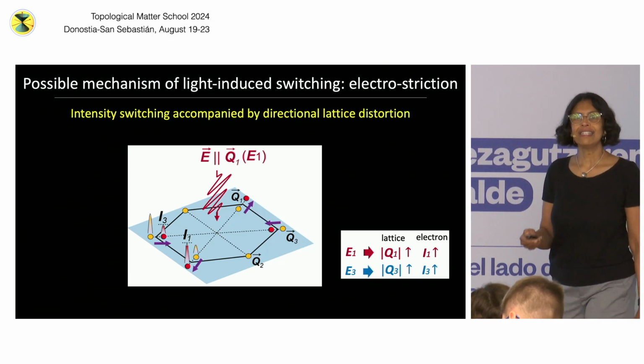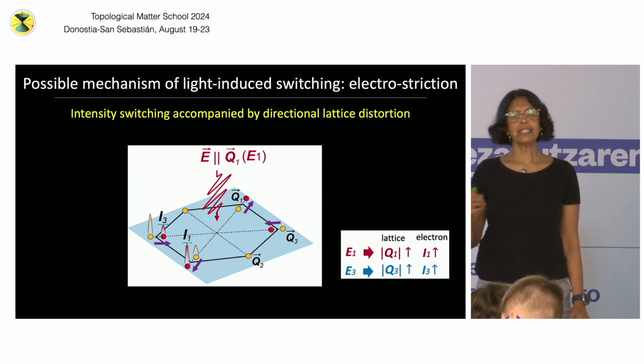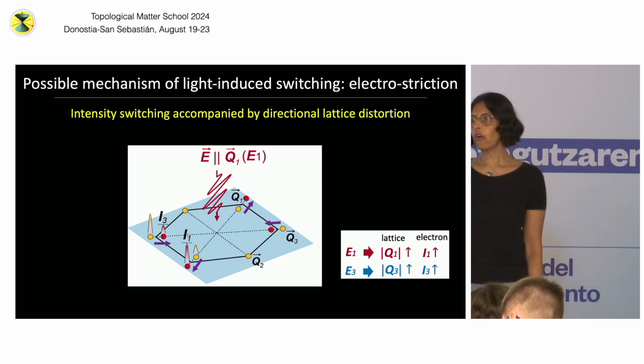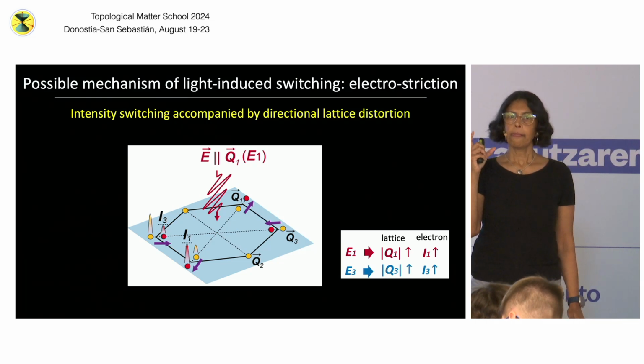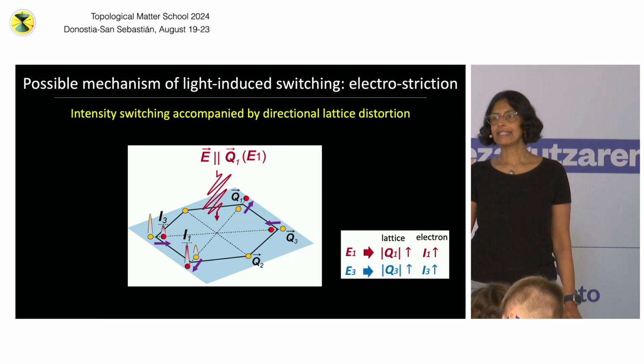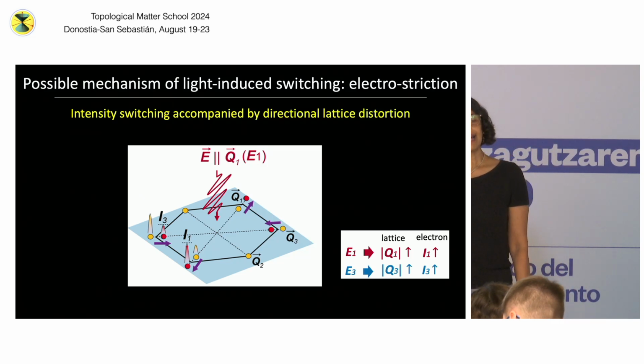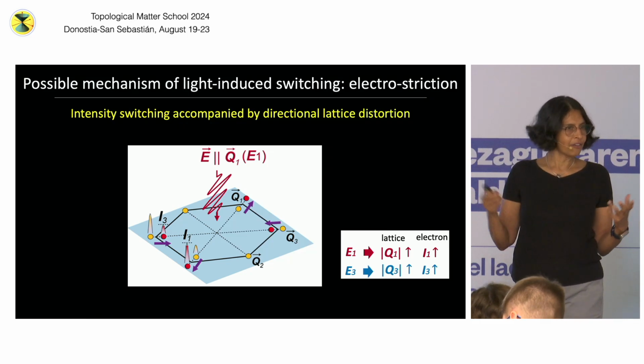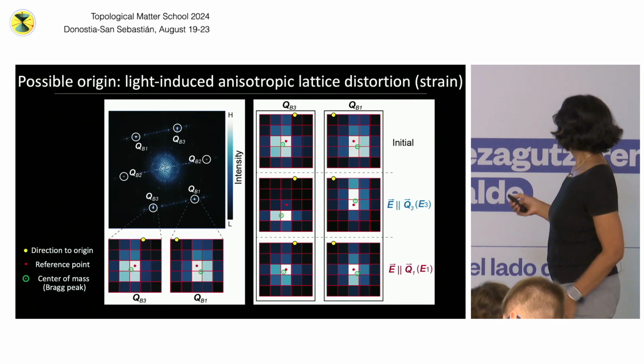So the question is, can we see this, right? If we could see that the atoms are distorting more in any given direction when the CDW intensity is higher, it means that this is something real. This is not an artifact of the tip, right? Atomic displacements are real things. So we can measure that.